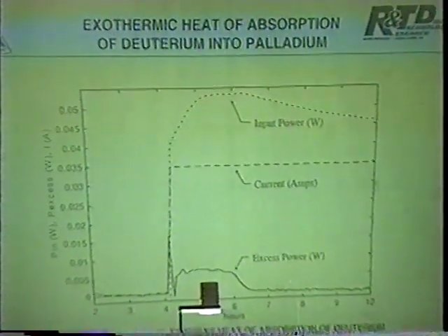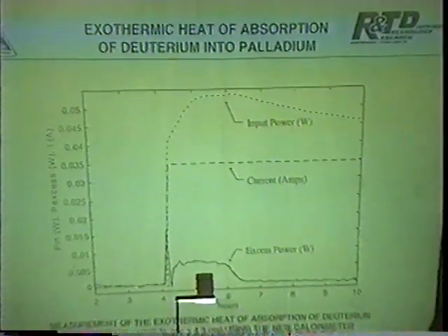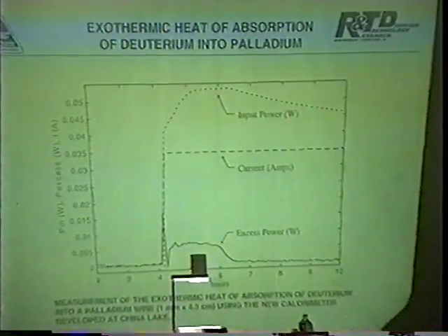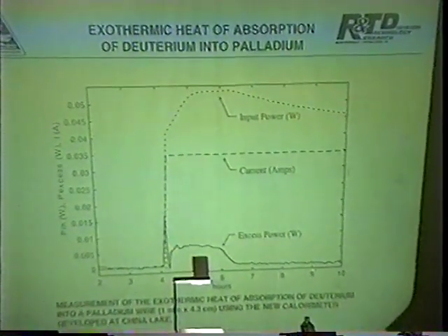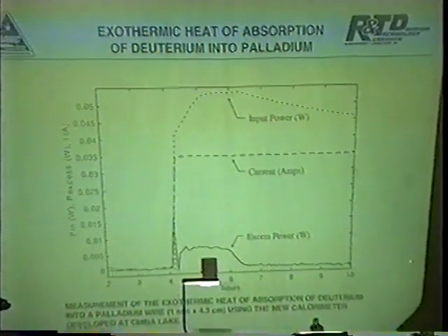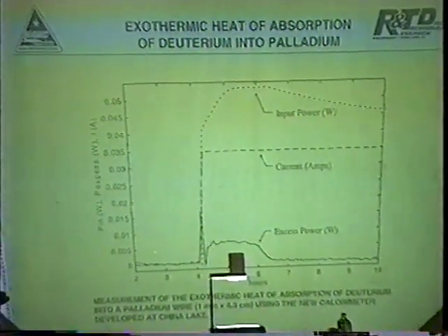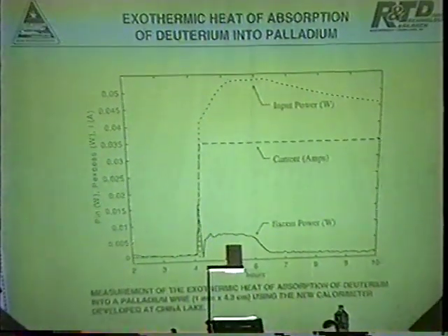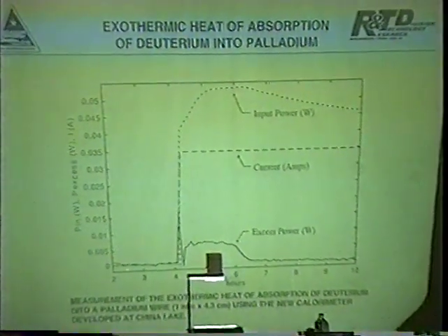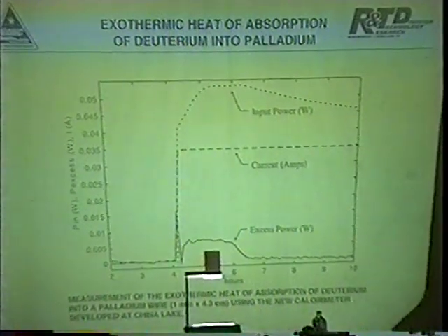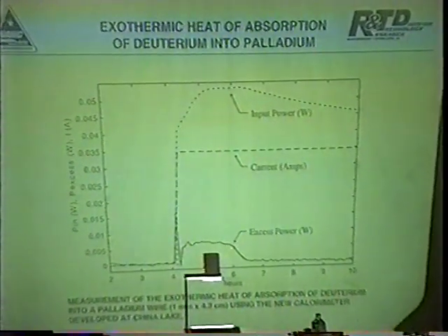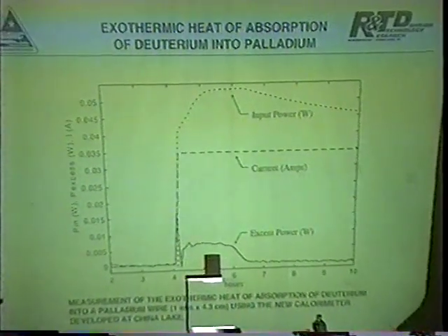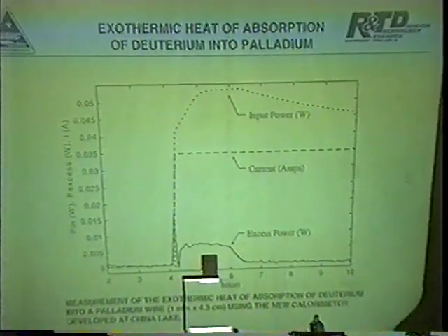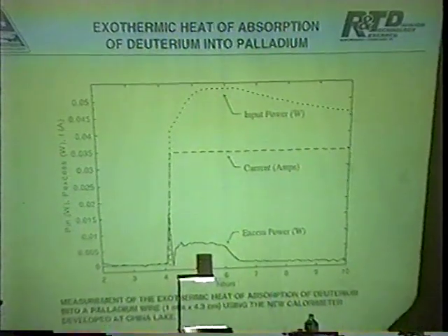Somebody asked about this, whether we have any negative effect early on. You see this is zero power right here. Except for the absorption of deuterium into the palladium, we do not see any negative effect. It's very, very level, very, very close. Notice that this is 5 milliwatts right here. So we're measuring very accurately. We get about a 5 milliwatt effect during the absorption of deuterium into the palladium. And this corresponds to loading to about 0.6. This little peak right here. So this shows the accuracy we can get with this new calorimetry. Okay, thank you.